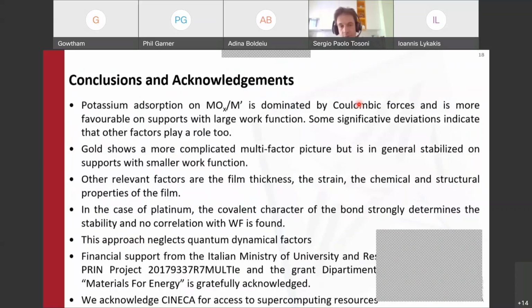And just let me throw in a few concluding remarks. As I said, potassium is adsorbed mostly as a potassium plus ion on most of the substrates that we considered, and its adsorption energy is strongly dominated by Coulombic forces, and it is more favorable on supports displaying a large work function. However, there are some significant deviations, implying that other factors may play a role too. For instance, the thickness of the film. The larger the distance of the potassium plus cation from the metal substrate, the larger the charge separation that we impose, and this is penalized by Coulomb's law.